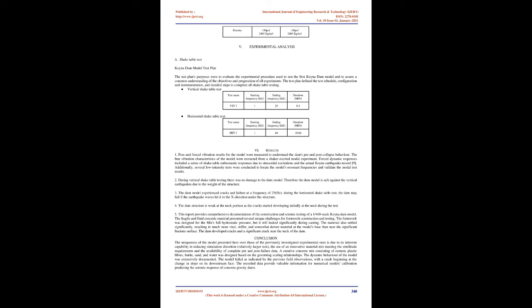6. Results. 1. Free and forced vibration results for the model were measured to understand the dam's pre- and post-collapse behavior. The free vibration characteristics of the model were extracted from a shaker-excited modal experiment. Forced dynamic responses included a series of shake table responses due to sinusoidal excitations and the actual Koyna earthquake record. Additionally, several low-intensity tests were conducted to locate the model's resonant frequencies and validate the modal test results.